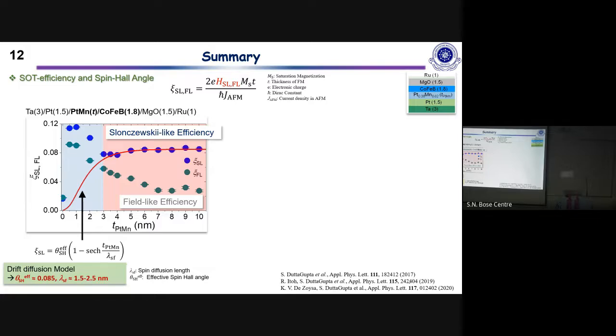This part you mean? Yeah. We actually think that in this portion there are probably contributions of the spin Hall effect also from the underlayers and maybe from the interface. So this model works only when you have bulk-type behavior. Once you go above 4 or 5 nanometers, it is flat. Also, the antiferromagnet becomes very disordered when you make it very thin, below 5 nanometers or so.